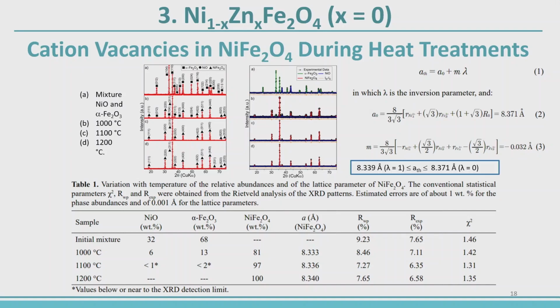Here, the first X-ray diffraction is for the simple mixture. The X-ray diffraction patterns for B, C, and D are for the different temperatures. This is Rietveld refinement. From there we determine the lattice parameter, and we can notice here that as the temperature increases, the lattice parameter increases. So we try to explain why this increase, or what this variation of the lattice parameter with increasing temperature is. We try to explain it using this well-known formula that is based only on cation reordering phenomena.